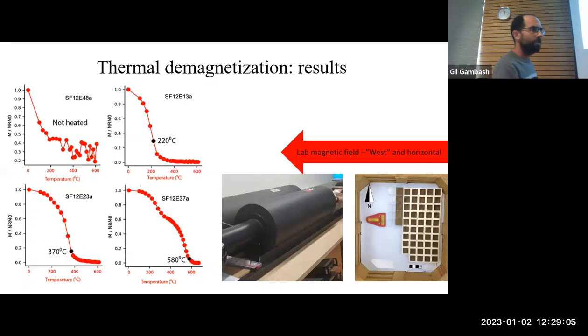You can see the y-axis is the magnetic signal, the magnetic moment normalized to the initial magnetic moment, so it always starts at one. And as we erase the magnetic field with the rising temperature, the x-axis, we gradually erase it. So the magnetic signal goes down as the temperature goes up, because this is again a zero field environment. You can see the not very nice behavior of the unheated bricks, but for the heated bricks from 100 degrees, here I put 220, but it's the same at 100 degrees, it goes down quickly. And then you have this knee where the magnetic field is not completely erased, but almost completely erased, and this knee is our estimation.